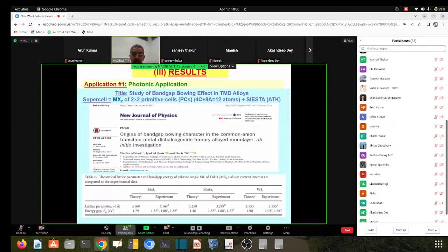The first application is photonic, where we study the band gap bowing effect in transition metal dichalcogenide ternary alloys. This paper was already published in 2021 in New Journal of Physics. We use transition metal dichalcogenides, maybe about 3 of them. And we use a very small supercell, a 2x2 primitive cell, which consists of 4 cations and 8 anions, 12 atoms. And we use SIESTA for that because we were lucky, me and Watha, that ATK was giving band gaps very close to the experimental band gaps.